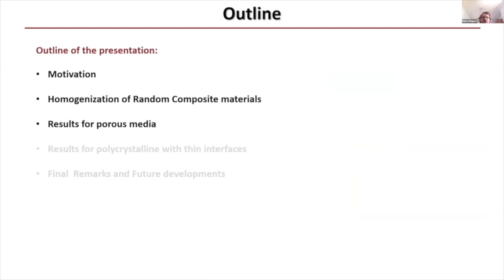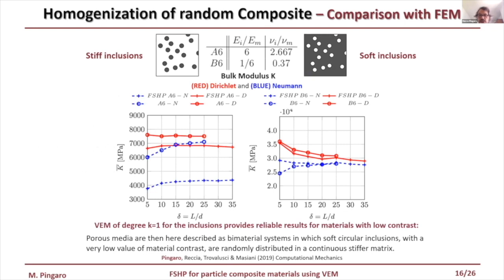Now I want to show some results obtained by the FSHP procedure. The first numerical result is a comparison between the previous procedure that used FEM of degree k equal to 2 and the new procedure with VEM of k equal to 1. We consider two types of materials, one with stiff inclusions and one with soft inclusions. The mechanical parameters are reported in this table.